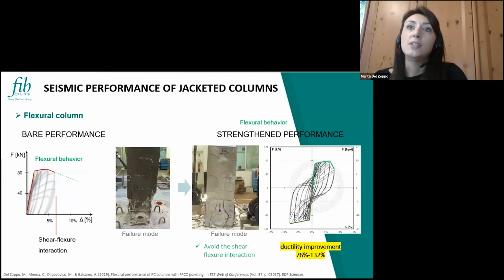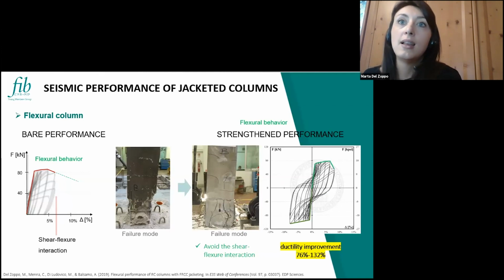And this is the failure mode of the jacket. Up to a certain level of deformation, we achieve the crushing of the jacket with a sudden loss in lateral capacity that is basically related to the strain softening nature of this material. When we have a crack in the jacket, it opens very fast after the bridging of the fibers. However, the jacket was able to prevent the shear flexure interaction that we observed in the bare column, and also significantly increase the ductility of the element.